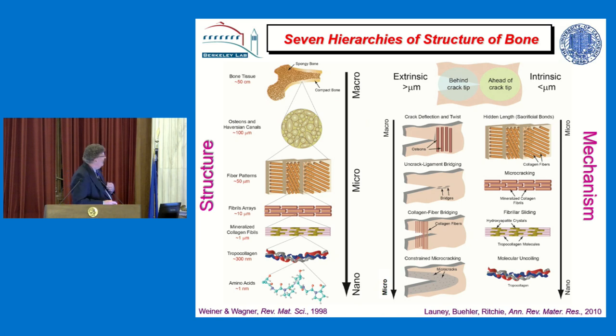So I did a study of this a few years ago to try and understand what are the various toughening mechanisms in bone. On the left side here are the different scales of bone. Again, the tropocollagen molecules, the fibrils, and the bone itself. And when we looked at the different mechanisms by which bone resisted fracture, if we look below about a micron scale, one of the things about bone is it's got all these different length scales, and each one develops a mechanism of toughening. If we look at a lot of engineering materials, they only have two or three length scales. Bone has at least seven, maybe more.